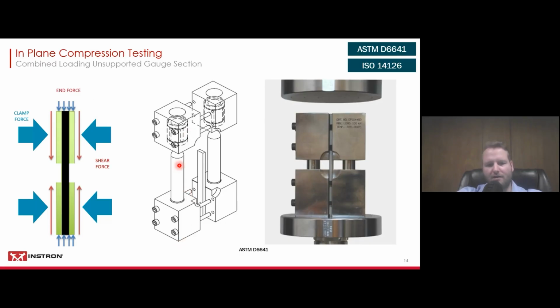So you have a bottom part with guide columns and then a top part, and you put your specimen in between. The inner surfaces are very rough to give you a nice coefficient of friction, so you don't have any slippage, and you make sure that your specimen is on a flat surface when you insert it, to make sure that you get that end loading portion on the bottom, and then the same on the top. You need to make sure that the end of your specimen and the ends of the top of the fixture are perfectly flush. And then combined, it looks like this between compression platens, and you would start compressing. And then the shear force comes through the torquing of these 8 bolts here. You have 4 in the upper part of the fixture and 4 bolts on the bottom part of the fixture. And that's where you're initiating the shear forces into your specimen.